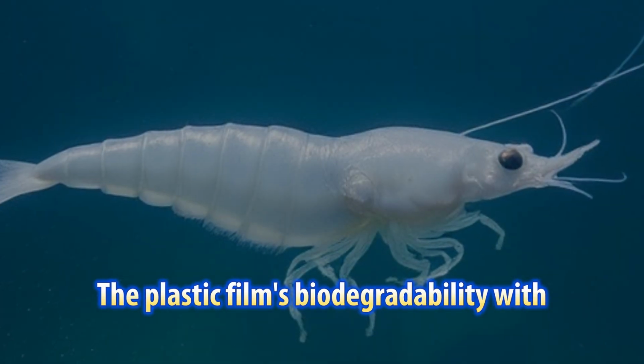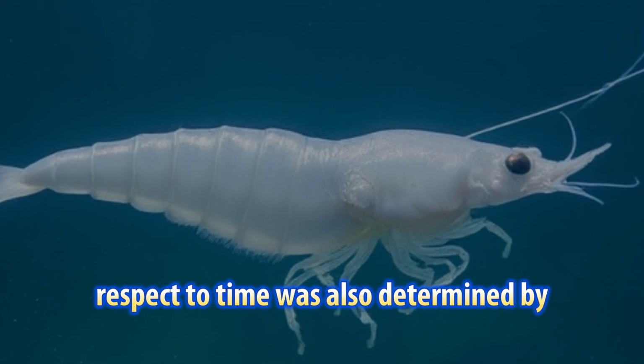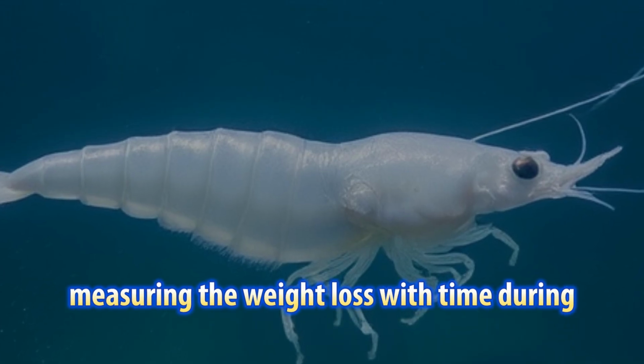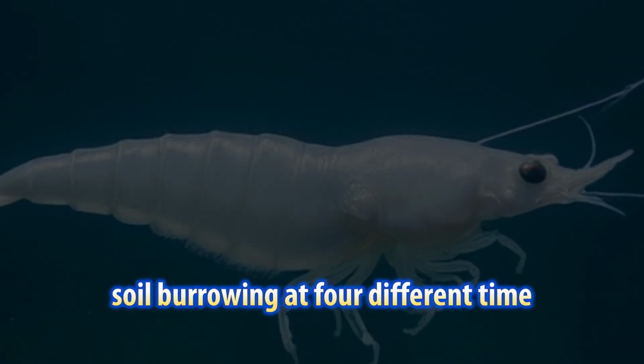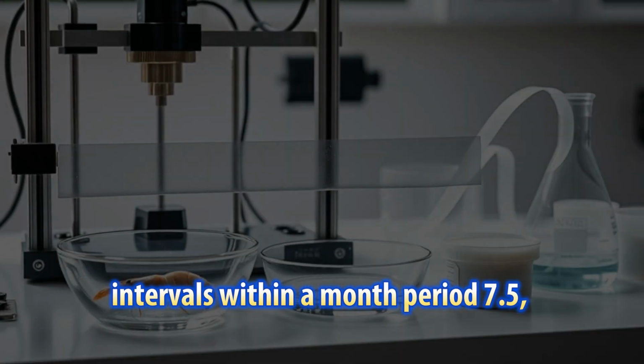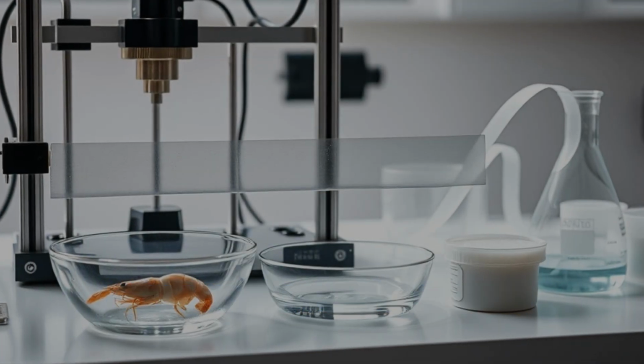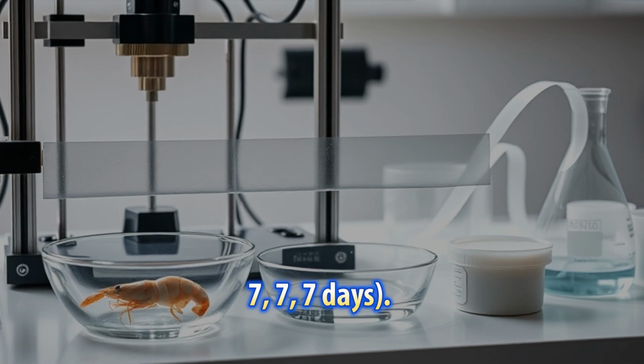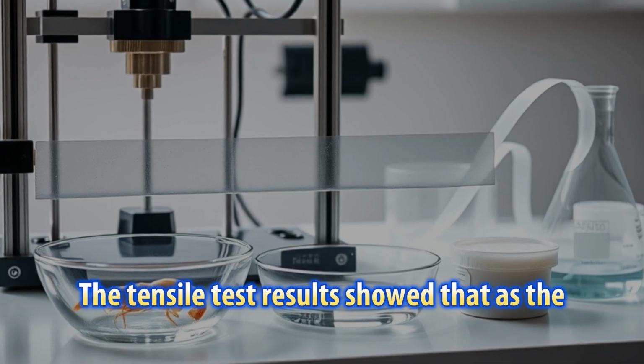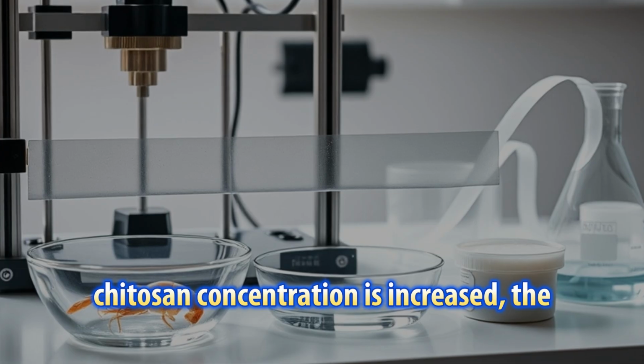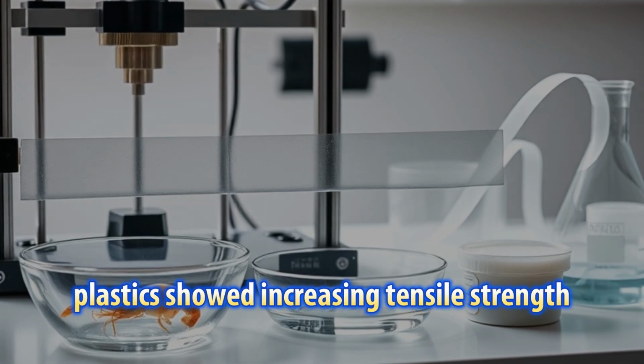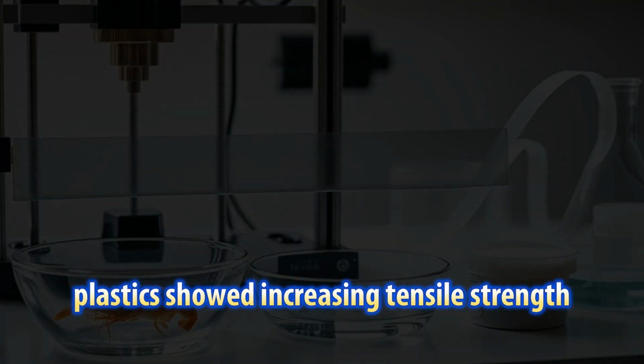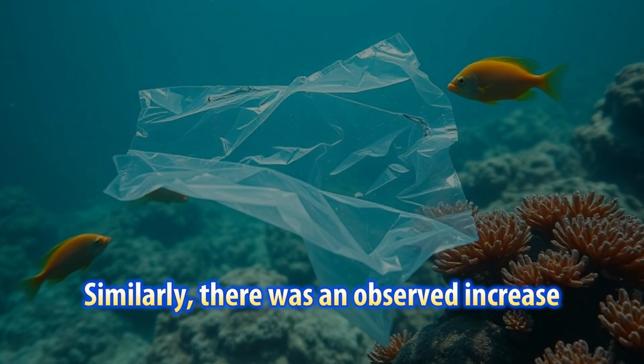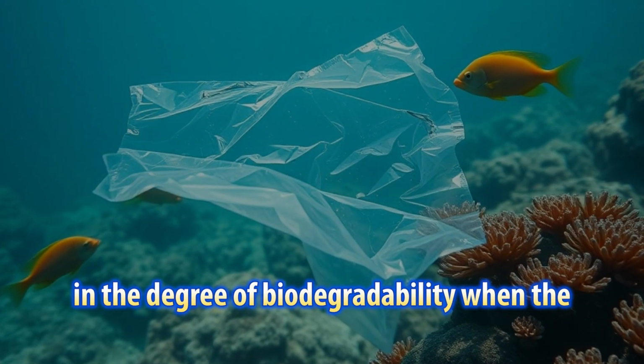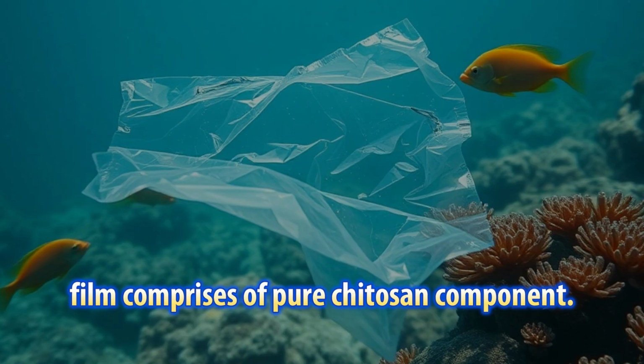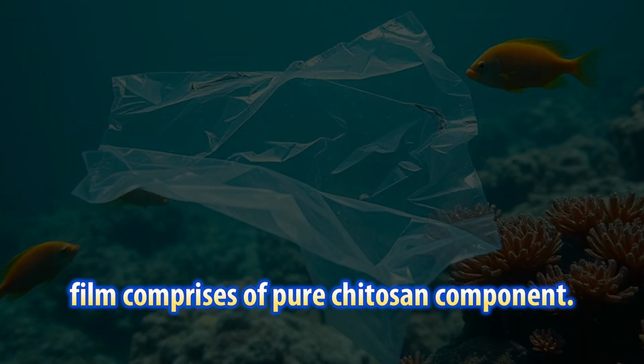The plastic film's biodegradability with respect to time was also determined by measuring the weight loss with time during soil burrowing at 4 different time intervals within a month period: 7.5, 7, 7, 7 days. The tensile test results showed that as the chitosan concentration is increased, the plastics showed increasing tensile strength values. Similarly, there was an observed increase in the degree of biodegradability when the film comprises of pure chitosan component.